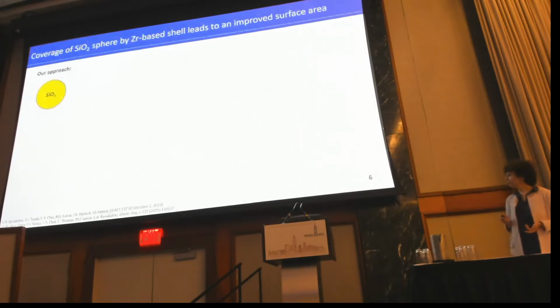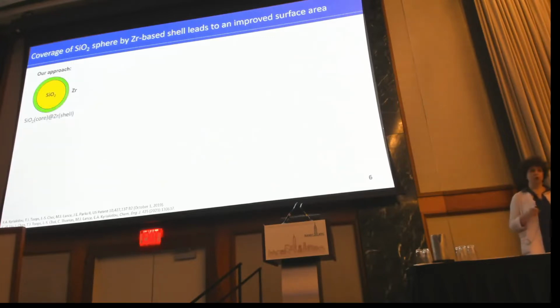And we did that by synthesizing silica spheres by the Stöber method, which is a known method, and then we deposited the zirconium layer on top of the silica sphere, and we created this so-called silica at zirconia core-shell structure. So just a little bit of